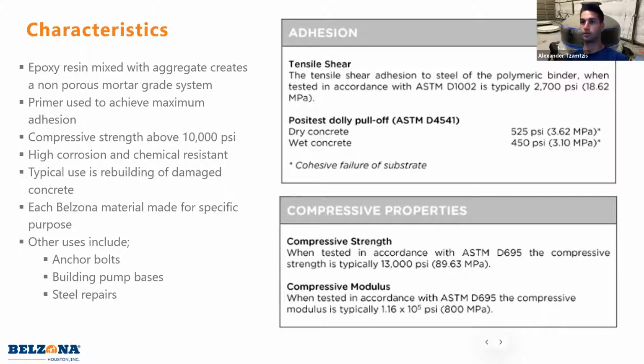and it's going to give you better properties. So your compressive strength is going to be above 10,000. You're going to have chemical and water resistance. And one of the great things is, like the video showed, the adhesion to concrete is greater than the tensile or cohesive strength of the concrete. So whenever we do our adhesion test and we pull the Belzona off, we actually pull the concrete off. So it's going to stick better to concrete than concrete would stick to itself.